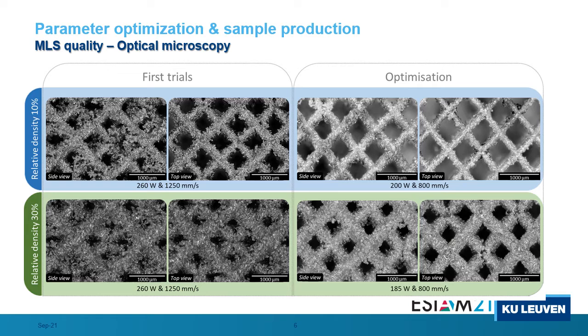On the right side, the coupons produced with the optimal parameter set are presented. In this case, the overall quality of the parts improved with a substantial reduction of the dross formation and of the molten particles on the strut surface. However, top view and side view show different strut thickness, indicating that the struts result slightly elongated along the building direction.